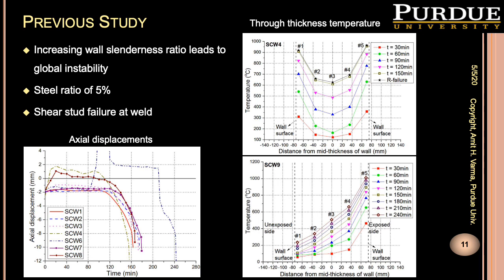When the heating is applied on only one side, for example, in specimen SCW9, what you'll notice is that the unheated or unexposed wall surface has lower temperatures, whereas the heated wall surface has very high temperatures. You're looking at the temperature profile through the wall thickness as the time goes from 30 minutes all the way up to 240 minutes.